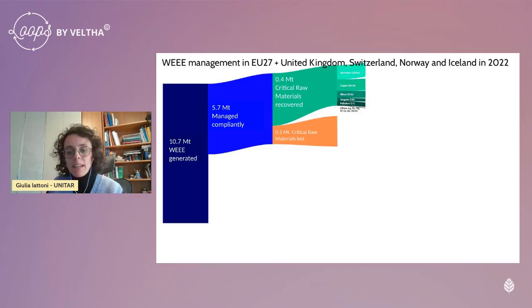Nevertheless, despite a compliant collection and treatment, still 0.1 million tons of critical raw materials could not be recovered and were lost during the process. And this is the case mostly for rare earth elements like neodymium, dysprosium, yttrium, which are present in small quantities but are vital materials found in permanent magnets, fluorescent powders, and other components.